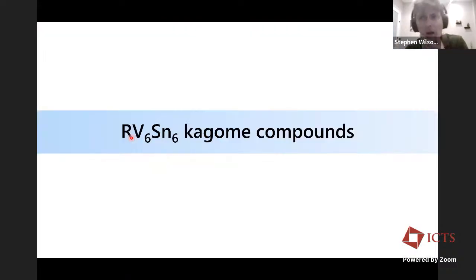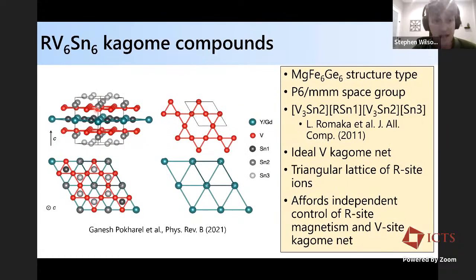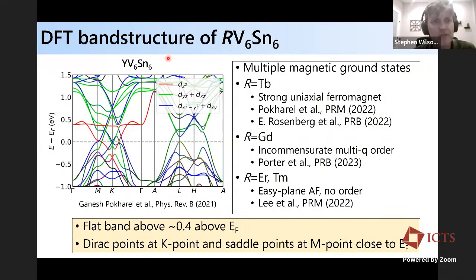Okay. So now what we wanted to do is to try and find other Kagome nets based on vanadium with a similar band structure, with Van Hove points fairly close to the Fermi level, which are also non-magnetic. One interesting class to try this are the so-called 166 compounds. Some people call these bilayer systems. So basically you have a Kagome net here and then a Kagome net here. They both have vanadium. And between these Kagome nets, you have a triangular lattice of rare earth ions. You can make that triangular net of rare earth ions non-magnetic by putting yttrium on it, for instance. But then you can also, in principle, control magnetism and interface it by adding magnetic dopants with these vanadium Kagome nets. And so the band structure of the yttrium system looks like the following.